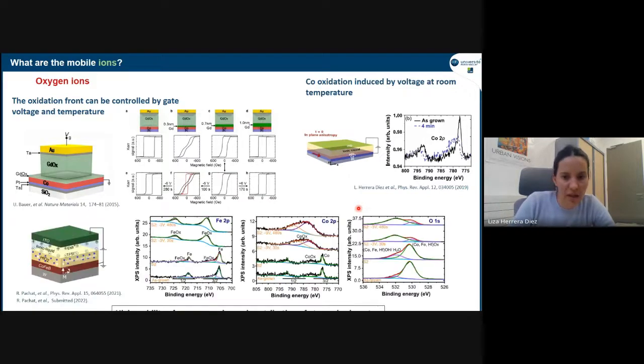And this is another example from one of our most recent studies on tungsten, cobalt, iron, boron. Here we have cobalt and iron. And we could also see by XPS that this is as grown, annealed. So we see that there's not much of a change in the oxidation level of the system after annealing. But then after electric field, there is an important change in the oxidation. We can clearly see how the oxidation of the iron and of the cobalt appear as a function of the electric field. And what is nice also is that the oxygen spectra also shows how the oxygen is being pumped into the system through electric fields.